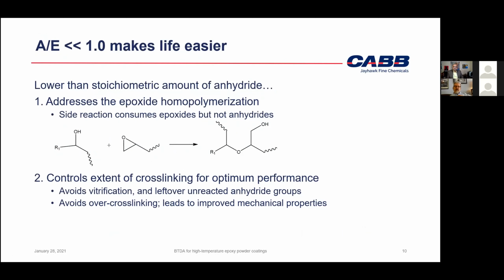Another thing to mention here, Vinay, is that we've got a lot of functionality here. When the anhydride opens up during the curing process, it's a very dynamic situation where you're going to start consuming functional groups. You're going to have chemical reactions right away, and what can happen, we know through experience, and you can do this analytically as well, is there comes a point where you have steric effects and diffusion effects where you just can't get those functional groups back together because you've already built a pretty high molecular weight network. So that's another factor when formulating these types of materials. We've got to look outside just the one-to-one stoichiometry.